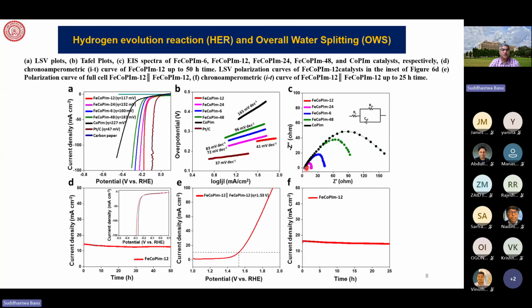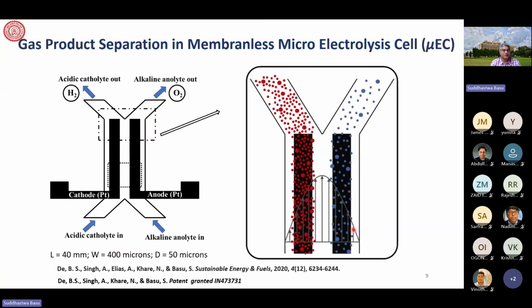Again, about the polarization resistance in EIS, electrochemical impedance spectroscopy, and many others that we have plotted here, iron plays a very crucial role, as we have shown you here when we work with EDTA. And so in a nutshell, what we are showing is that we were able to make a catalyst which not only works for the oxygen evolution reaction, but also works for the hydrogen evolution reaction as well. It's the same catalyst. Now, this was the catalyst development.